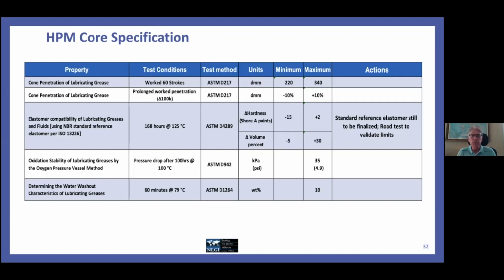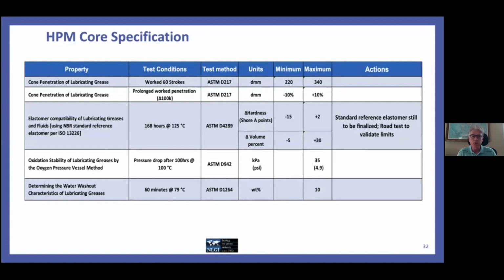So another change from GCLB here is that in GCLB, we do not specify 168 hours at 125C. In fact, we've increased the time duration and lowered the temperature. So we need to collect some data to validate this. So when we get the elastomer finalized and in place, we say something there under actions called road test to validate limits. So some of these tests where we simply do not have the data to say these are the right limits. For instance, we don't have data on this new elastomer at 168 hours at 125 C.